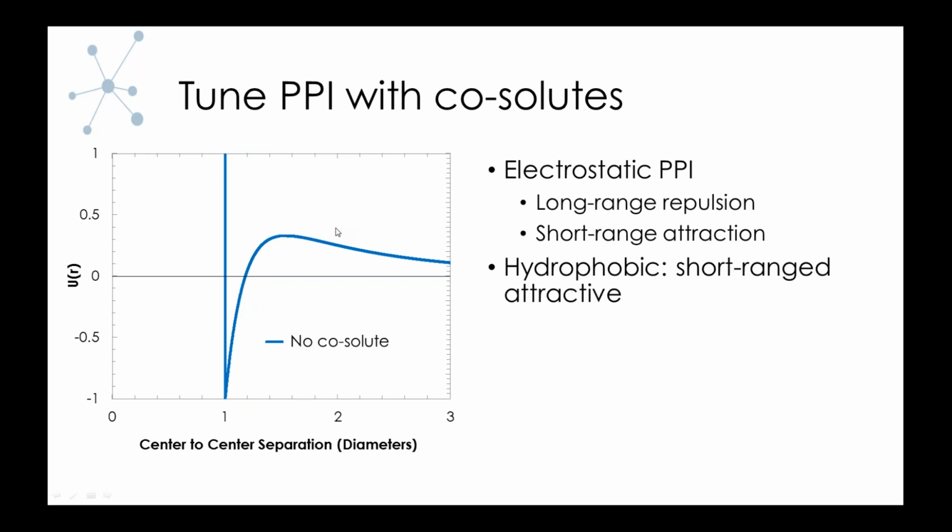On the left here, I'm showing a purely hypothetical, very oversimplified model of the potential interactions of proteins. As you can see, at very short separation distances, within a particle, these are dominated by hard particle-like repulsion. However, as you get just away from the surface, so now that these surfaces are nearly in contact with each other, you have these short-ranged, very strong, attractive interactions which form this attractive well. But as you get further away from the surface, the strength of these attractions becomes much weaker. And now the proteins are able to diffuse and rotate freely.